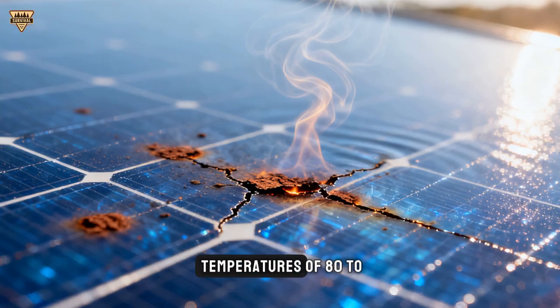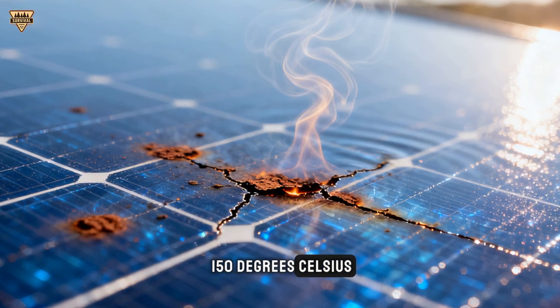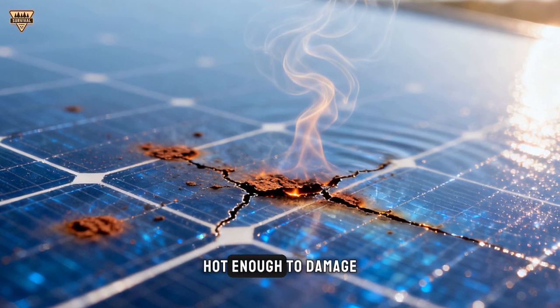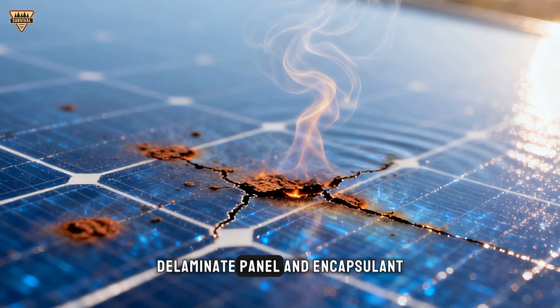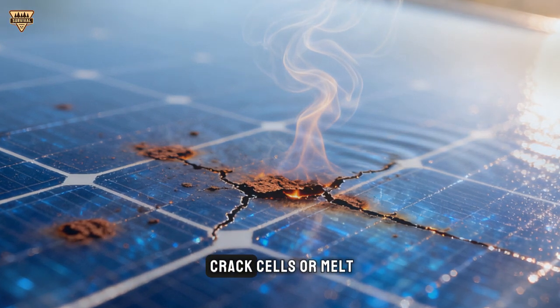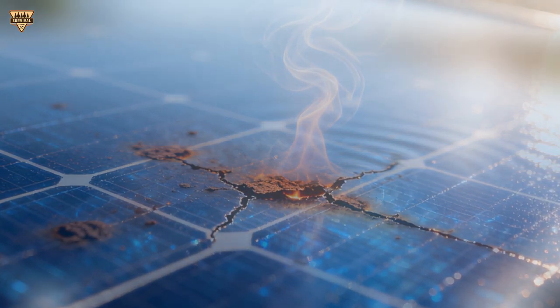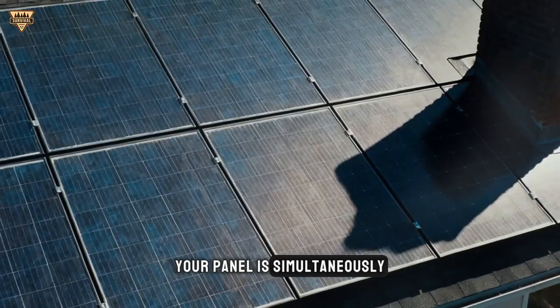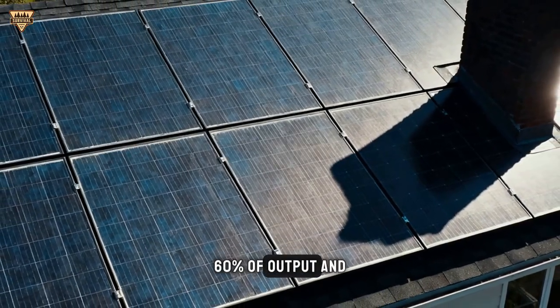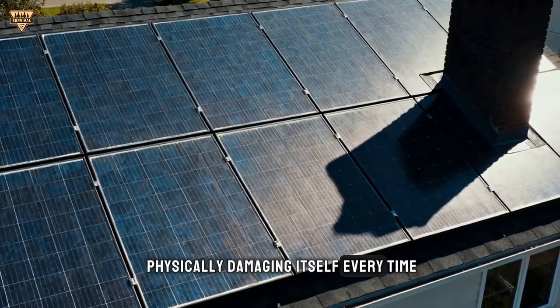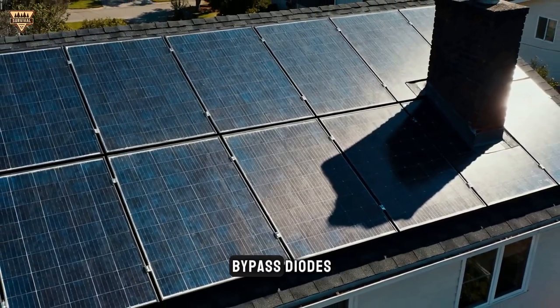Shaded cells can reach temperatures of 80 to 150 degrees during hotspot conditions, hot enough to damage cell material, delaminate panel encapsulant, and in severe cases, crack cells or melt solder connections. Hotspot damage is cumulative and permanent. Your panel is simultaneously losing 30-60% of output and physically damaging itself every time partial shade occurs without bypass diodes.